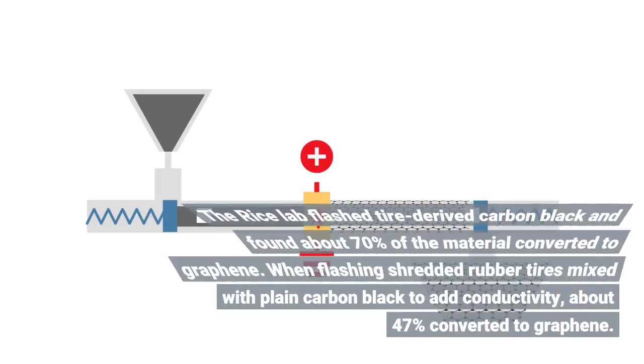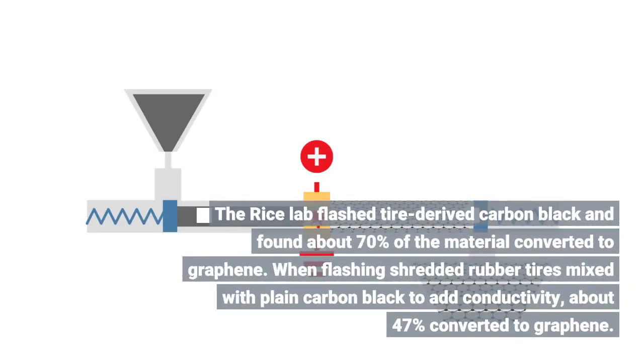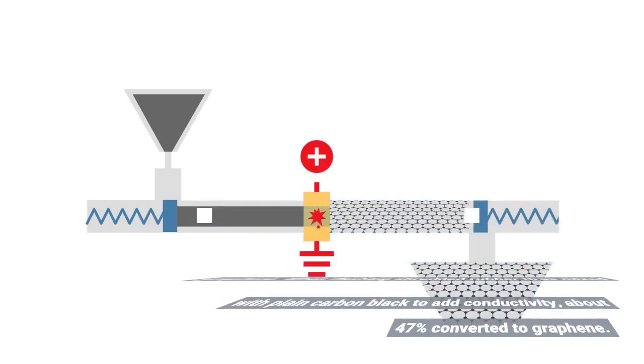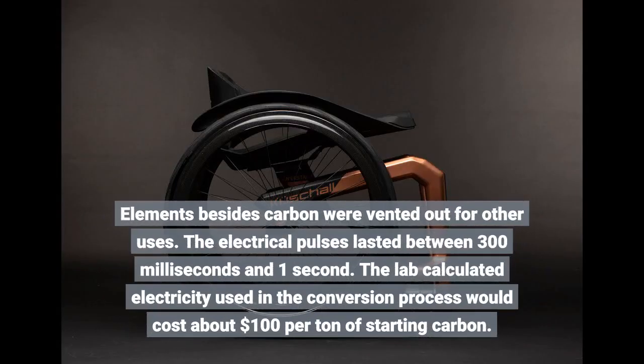The Rice Lab flashed tire-derived carbon black and found about 70% of the material converted to graphene. When flashing shredded rubber tires mixed with plain carbon black to add conductivity, about 47% converted to graphene. Elements besides carbon were vented out for other uses. The electrical pulses lasted between 300 milliseconds and 1 second. The lab calculated electricity used in the conversion process would cost about $100 per ton of starting carbon.